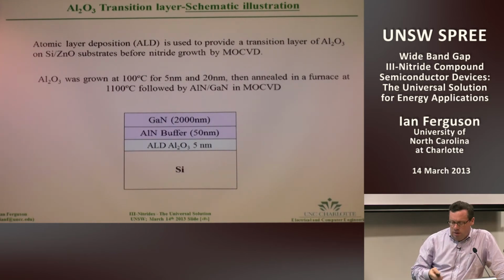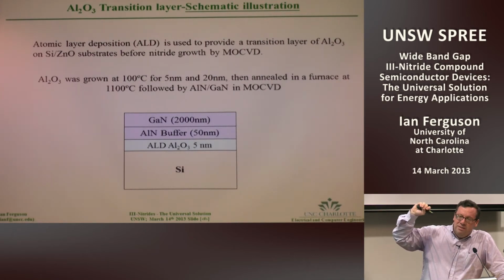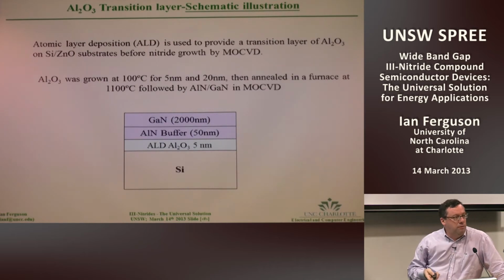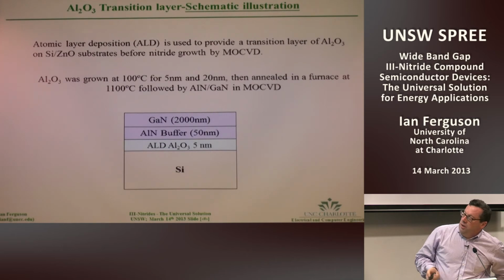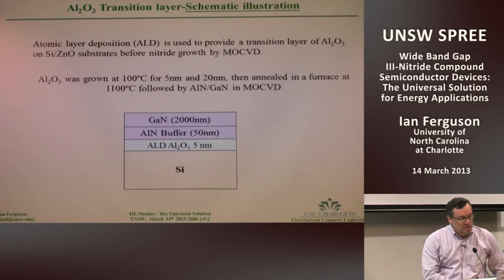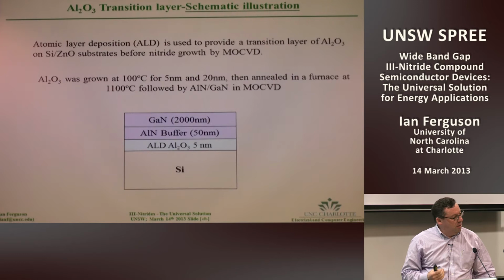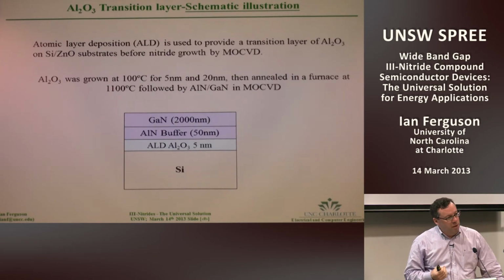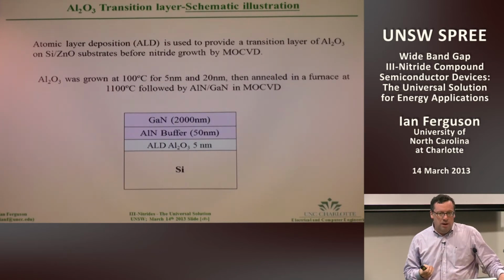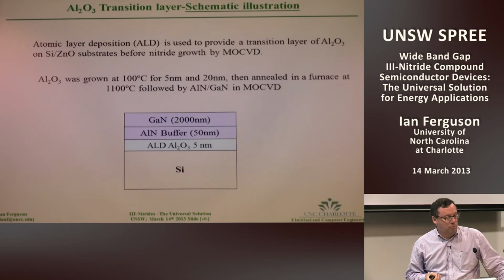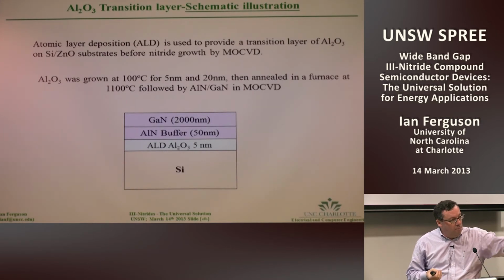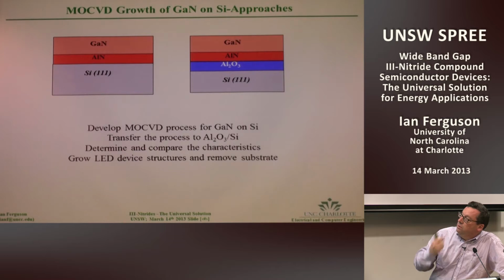There's an Australian company, BluGlass, who do similar types of things, but different. Our devices are always crystalline. So our aim here was to simplify the growth on silicon, where you have to deal with thermal mismatch, and with polar, non-polar growth, where you get low angle grain boundaries and other things that form within the material.